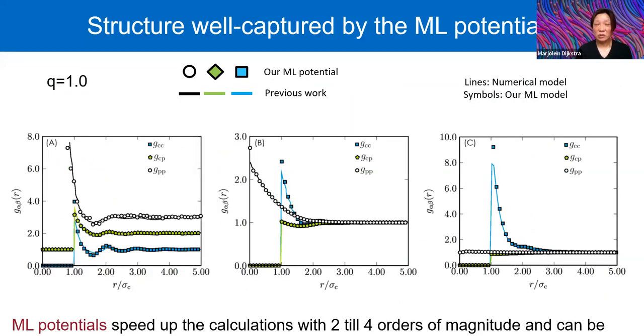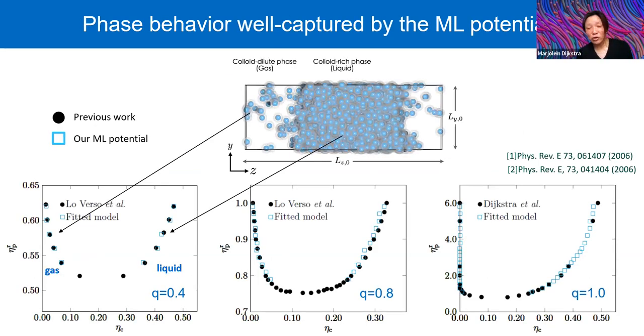Here we performed simulations using these machine learning potentials, and we compared the radial distribution with previous work where the full binary mixture was simulated. What we find is that the machine learning potentials really speed up the calculations by up to four orders of magnitude, and the structure is really well captured by these machine learning potentials. This is for a size ratio of one, where the colloidal particles are as big as the polymer coils. In this case, the many-body interactions are really pronounced. Because we can assume these machine learning potentials to be state independent, this is very nice because we can then also perform direct coexistence simulations in an elongated box.